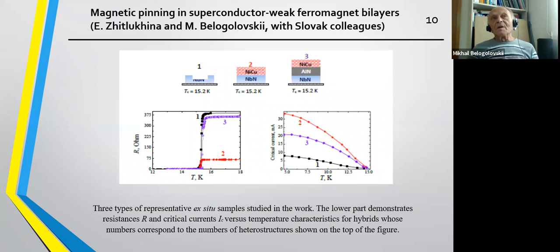So how is it done? Often it is done by introducing pinning centers that immobilize the vortices, so the critical current is increasing. In our case, it was experimentally realized in Bratislava.